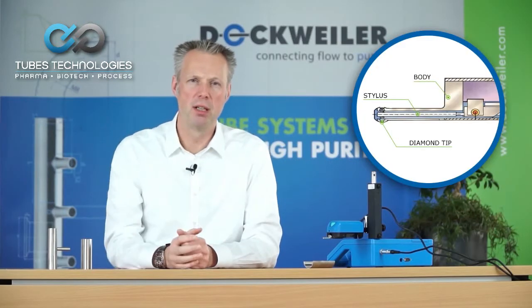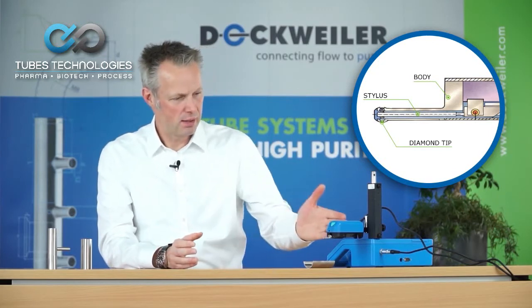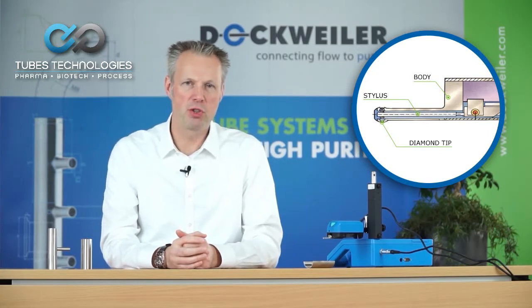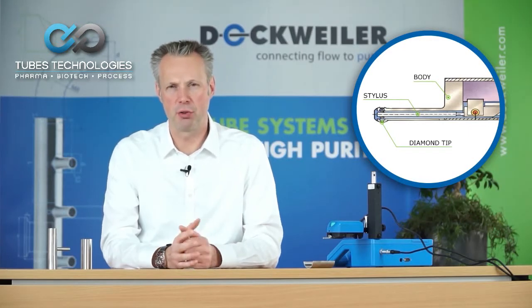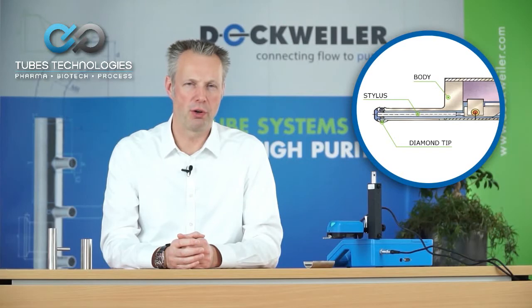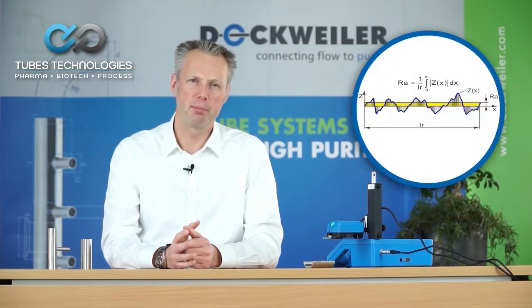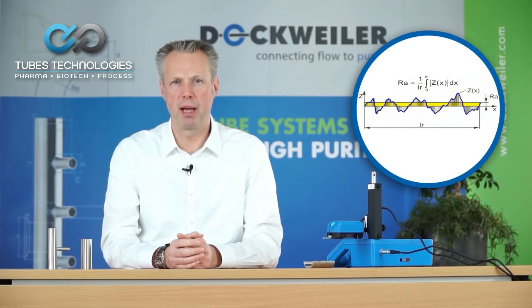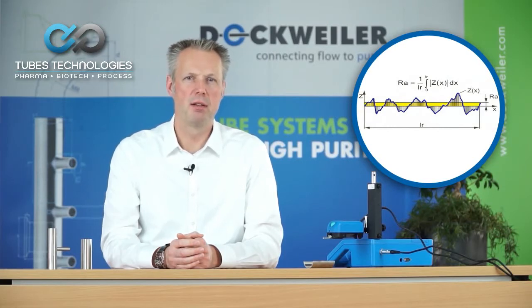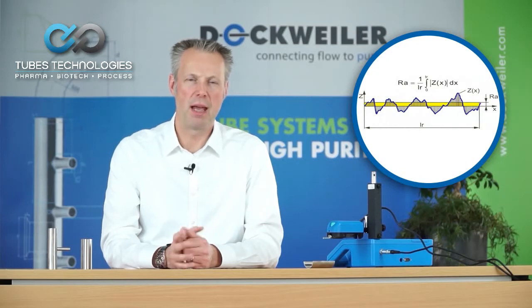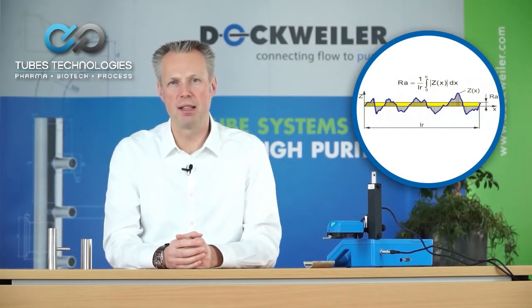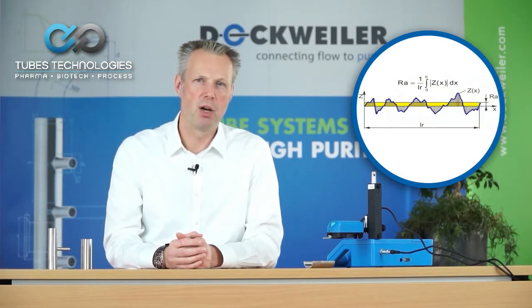On the upper picture here, you can see a cross-section of this measurement head, which consists at the end of the day of some electronics and of the diamond tip in front. In another picture, you can see the actual travel path that this diamond tip is performing on the surface. The RA value at the end of the day is nothing else but the arithmetic average of the displacement of the diamond tip on this surface. So with this you have information about the roughness of the surface.